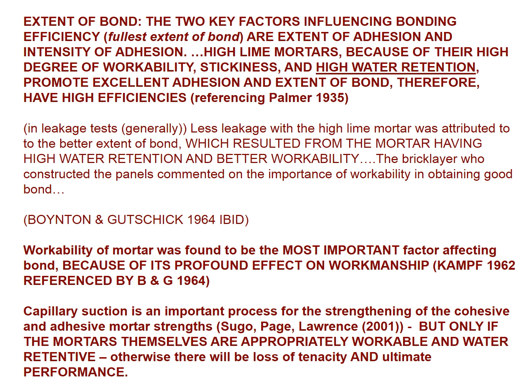The two key factors influencing bonding efficiency are extent of adhesion and intensity of adhesion. High lime mortars, because of their high degree of workability, stickiness, and high water retentivity or water retention, promote excellent adhesion and extent of bond, and therefore have high efficiencies.